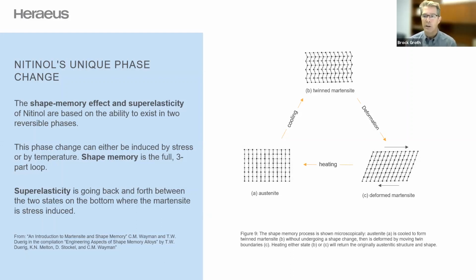If you cool that material down, the crystalline structure changes to martensite, but just in cooling the material, the bulk shape is still represented here as a rectangle. The wire will not have changed shape just by cooling it. So now if you deform this cooled wire, this shape memory wire, you move to the lower right-hand corner. Now the whole shape has been turned into a parallelogram. That again represents the bulk shape, the wire being bent, the stent flexing, whatever. But also the inner crystalline structure has changed. It's now this aligned parallelogram shape, and that is the martensite shape.